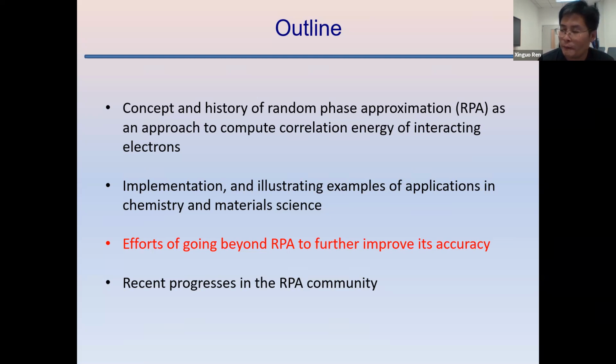But for systems which have quite strong correlations, where GGA is not a good starting point to quantitatively describe the systems, one may prefer hybrid functionals. When we do this for correlated materials, GGA seems not a very good starting point. So I would prefer to use either Kohn-Sham or a hybrid functional with a small mixing parameter. These are typically good starting points for RPA.